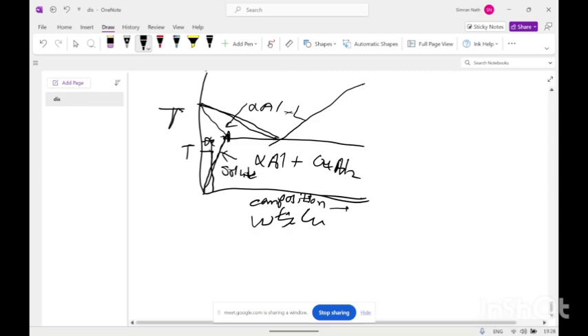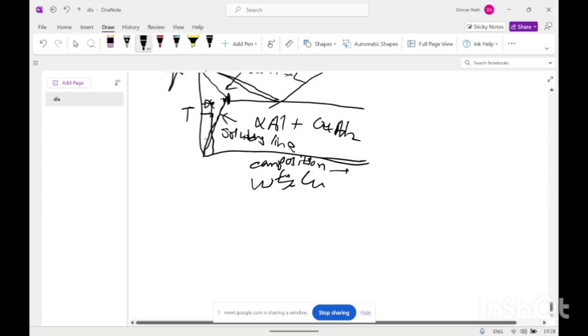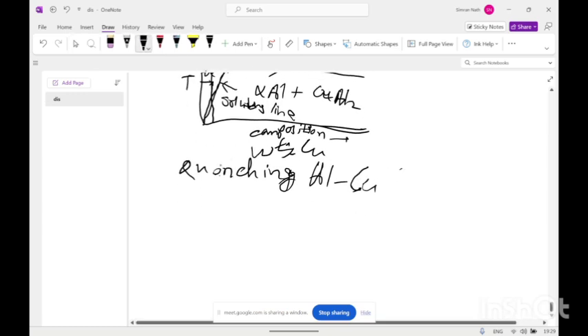From this solvus line we can see that with decrease in temperature, the solubility in aluminium decreases. If we heat an alloy of a composition up to the single phase region and quench it at a high cooling rate, all the solute is entrapped in the aluminium-copper solid solution. All the copper is entrapped in the quenched composition. So the quenched alloy is called the supersaturated solid solution, meaning the copper concentration is maximum in it.